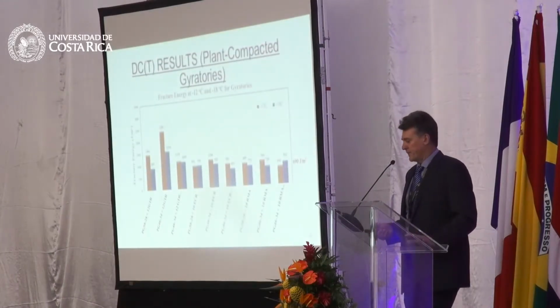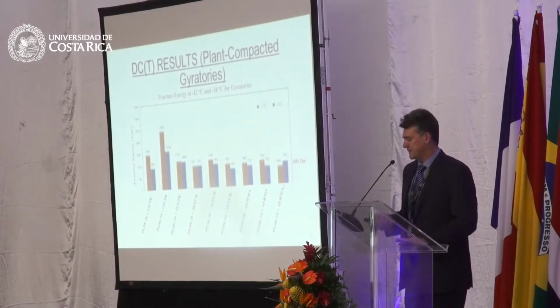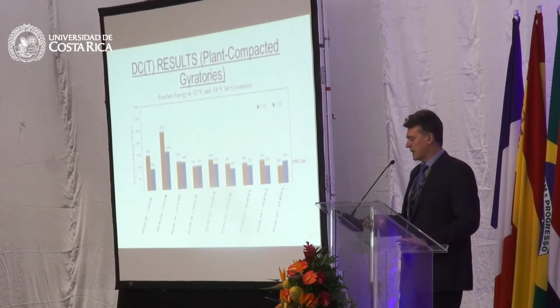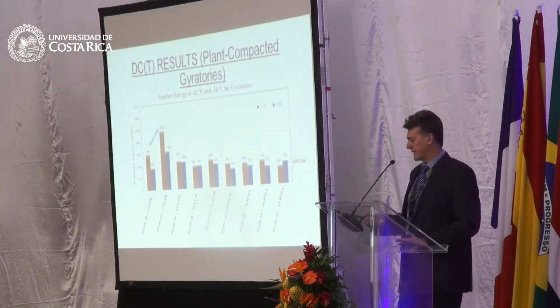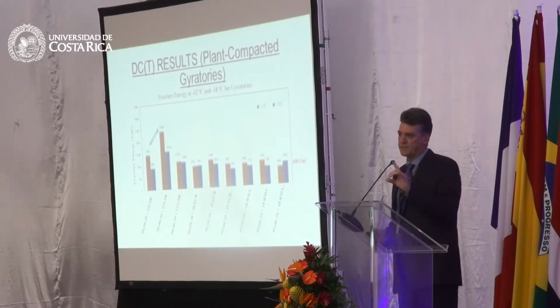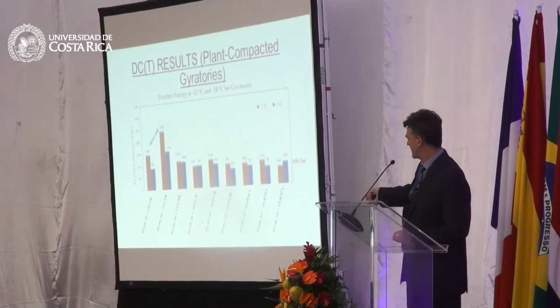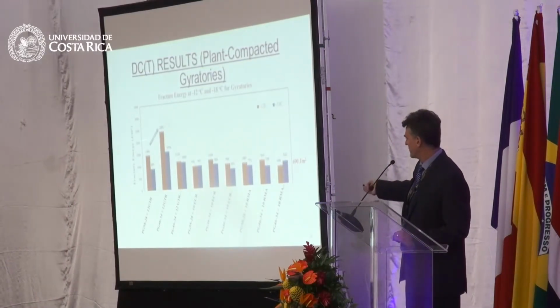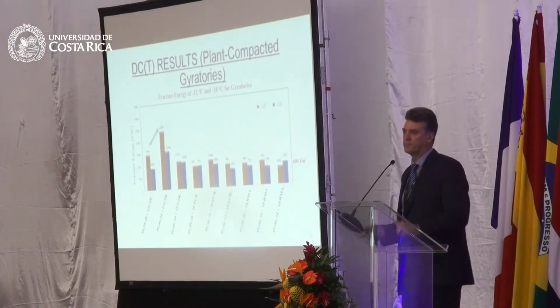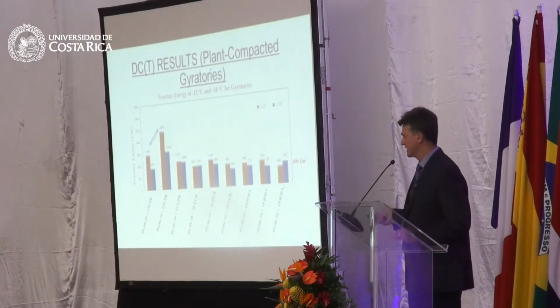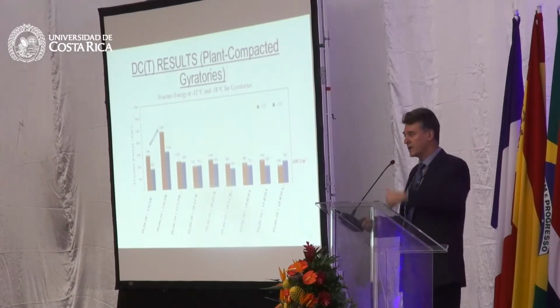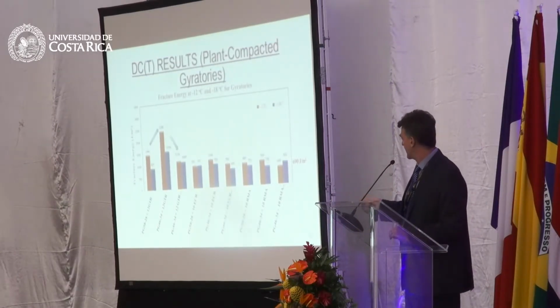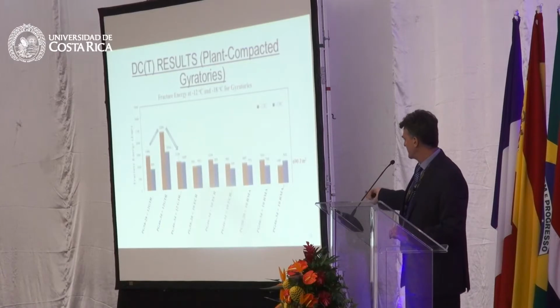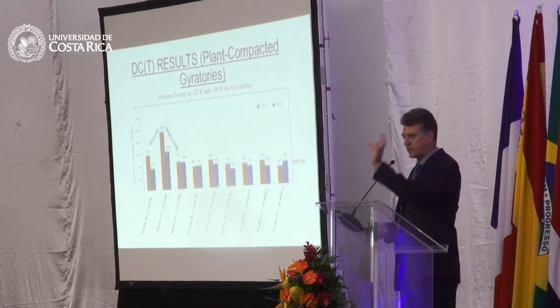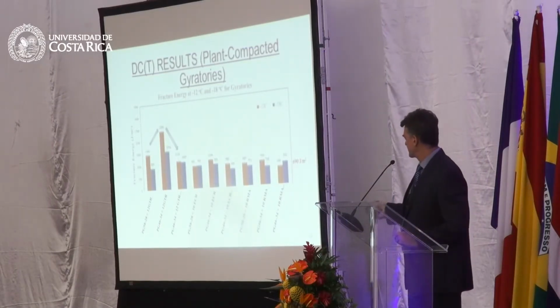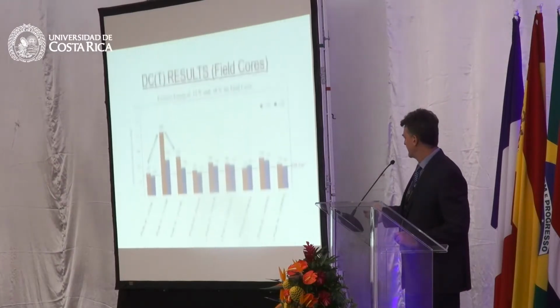Looking at the fracture results first, this is the DCT fracture results. These are on the plant compacted materials, and the trend we expected to see is when we went from the -28 binder to the -34 binder, we expected to see a pretty big boost in fracture resistance or fracture energy. But then as we added higher recycling, we expected it to come back down, and that's what you saw. And for each of the three conditions for the mixtures, you saw the similar trend.